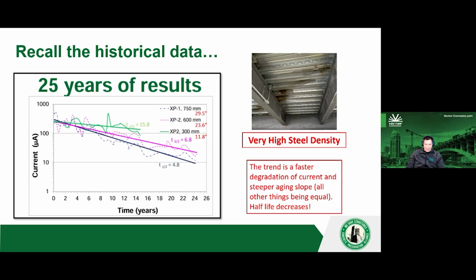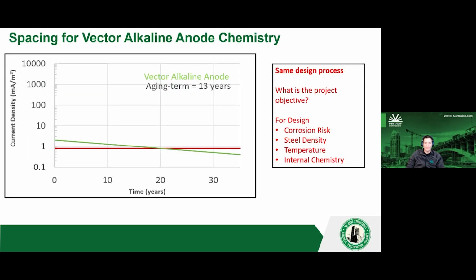One of the caveats here is that there was very high steel density. I mentioned it. This pan decking is connected to everything electrically. So the trend is a much faster degradation of current and a steeper aging slope. All other things being equal, the half-life really decreases in this case. So going through this design process, they wanted 20 plus years. Corrosion risk was high. Steel density, very high, especially that pan decking in there. Temperature, same-ish as the other two. Internal chemistry was the same. It makes this aging term much, much smaller.